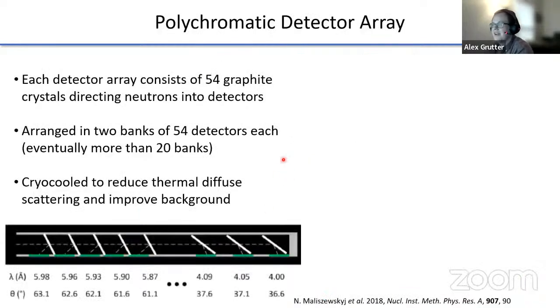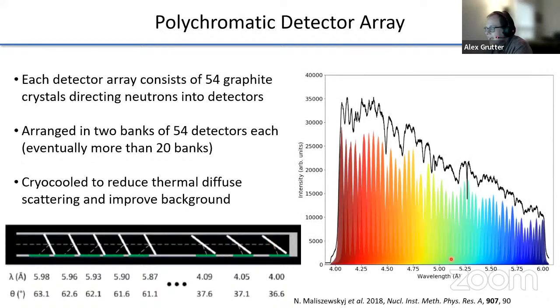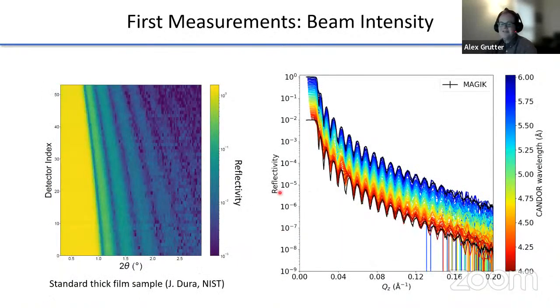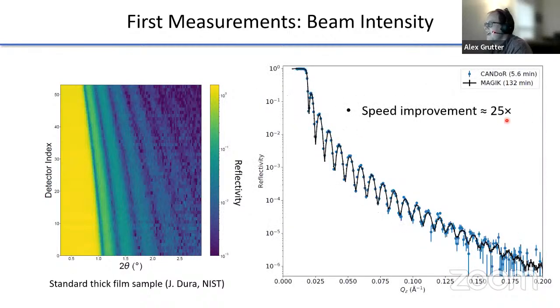Center for Neutron Research. And so the idea here is that on the back end, you have an array of 54 graphite crystals that are picking off individual neutron wavelengths and sending them into a bunch of different detectors. And so here you can see the detector response where each of the individual detectors picks out a different wavelength. And what this really gives you is 54 neutron reflectometers all stapled together. I'm a little behind schedule here, so I'm going to fast forward a little bit, but the basic idea is you can then combine data from all 54 of these reflectometers to get something like a factor of 25 improvement in intensity.